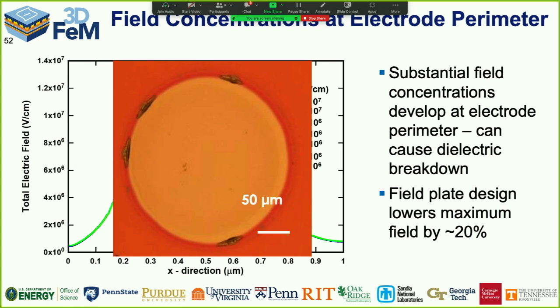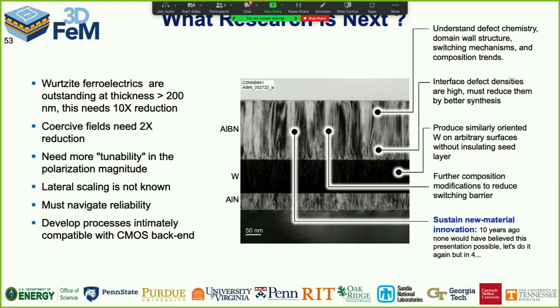And we're starting to get rid of that problem where those black specks, we've literally blown the material up and removed the electrode. You'll notice all those failure events are around the electrode perimeter where the field concentrations are the worst. So we have lots of extra work to do here. We've nowhere near begun to probe all of the things that we need to do. Among the things that are really critical is to improve the crystallography of that very first interface between the bottom electrode and the aluminum nitride. And so that's where we're poking at now.